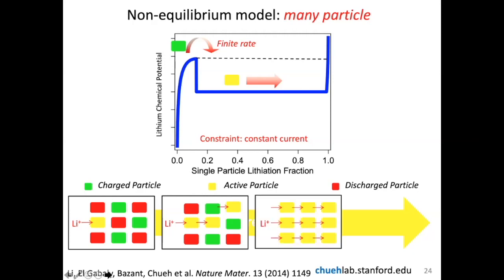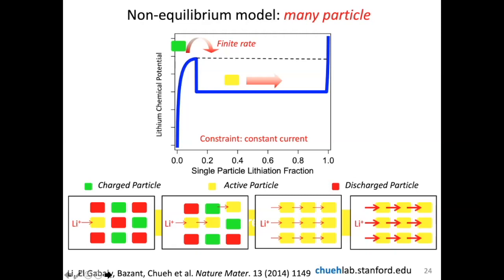And as you increase the driving force, you don't increase the rate of the phase transition. Instead, you increase the rate of nucleation. So the result is that you increase the number of active particles, but you don't increase the current per particle. So this precisely explains the population behavior we saw. We saw that the material accommodates additional current by increasing the uniformity of the reaction rather than increasing the rate of individual particle proceeding.